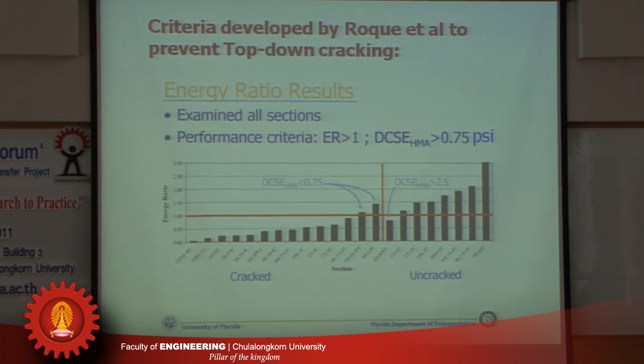So this ratio has to be greater than 1. This means that the DCSE has to be greater than the minimum DCSE, and the formula for the minimum DCSE was given in the previous slide. And also the DCSE needs to have a minimum amount, which is 0.75. So basically, in his recommended method, you would test the mixture and make sure that the mixture would have a DCSE that's greater than the minimum DCSE, and also that DCSE has to be at least greater than 0.75. And with this criteria, we can predict whether or not we may have likelihood for top-down cracking. And the predicted result matches very well with the observed result.